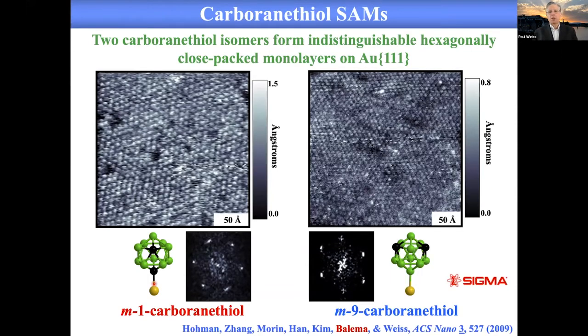And so by tuning the electronic properties of these molecules by design, by putting, for instance, the carbon atoms at the top of the molecule away from the surface, that makes the surface positively charged. By putting the carbon atoms on the side, that makes the surface nonpolar. And if we put the carbon atoms at the bottom, then that would make the surface negatively charged. And we're able to tune the surface charge just by choosing the molecules that we use, and you'll be able to figure out where we're going in terms of band alignment. We can see those effects at both the macroscopic scale and at the nanoscopic scale.